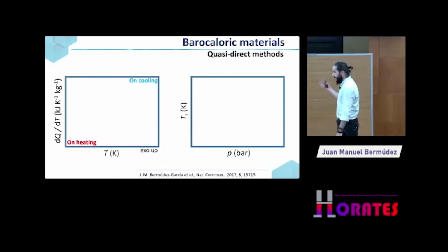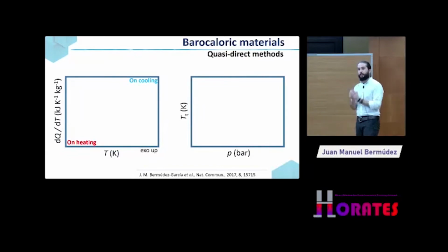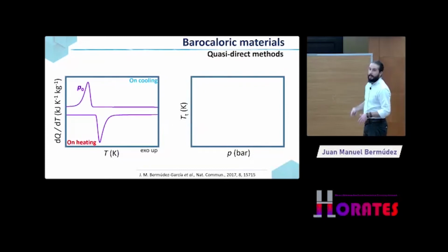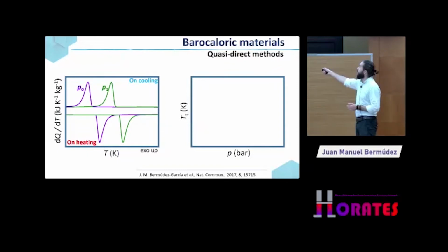There are other types of differential scanning calorimeters that are also coupled with pressure cells, but these pressure cells cannot control a pressurization ramp, but they can provide isobaric conditions. So you put a fixed pressure inside this cell, and then you do temperature ramps, like in a traditional DSC, okay? So in that way, what you have is a heat flow as a function of temperature on heating and cooling, but for different pressures. You start at ambient pressure with a run or a scan, then you increase the pressure, keep it in isobaric condition, and keep changing this pressure, right? So you have a standard DSC, but at different pressures.